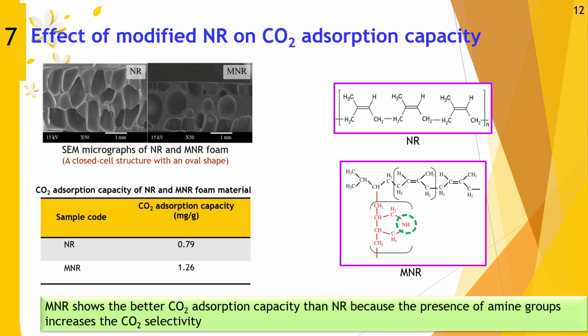Here, the SEM image of the natural rubber before and after modification are shown in this figure. Both natural rubber and modified natural rubber show a closed cell structure with an oval shape. However, the cell size of the modified natural rubber foam is smaller than that of the natural rubber foam. And the carbon dioxide adsorption capacity of modified natural rubber is higher than that of the natural rubber foam. It is because the presence of the amine group increases the carbon dioxide selectivity of the material.